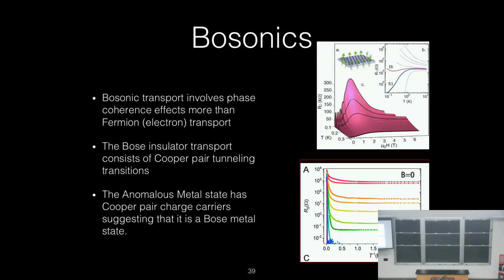What about on the overdoped side, when you go to this non-Fermi transport, when you get this linear resistivity? Can you see something there? So these were optimally doped films. I don't know if the group is trying to make underdoped films or not. You want to do overdoped, where it's a really good superconductor. Plus when you get this regime where you have linear resistivity with temperature. Actually, the cleanest films here, the ones that are least damaged, show that linear resistivity. But you can see that in regimes even at low temperatures when you go to the overdoped side. If you put on a big magnetic field, it continues down. Is that what you're saying? Even with this higher dome. Okay. I'll have to look at that some more. That could be interesting. That crossover too. Oh, thank you.